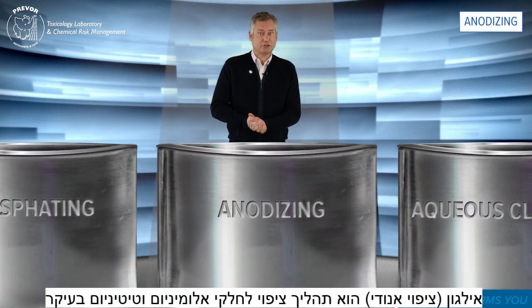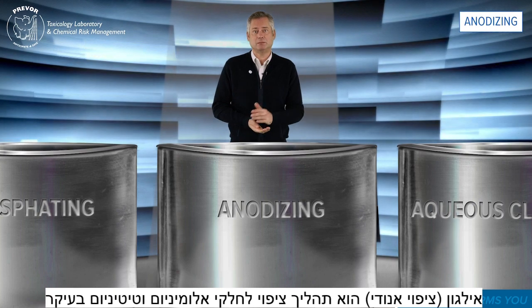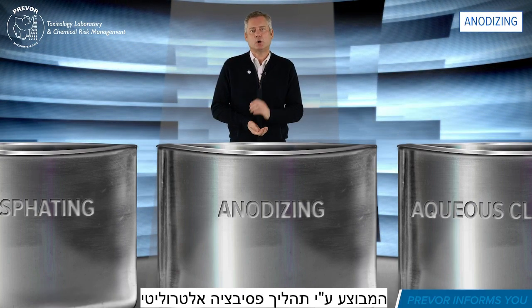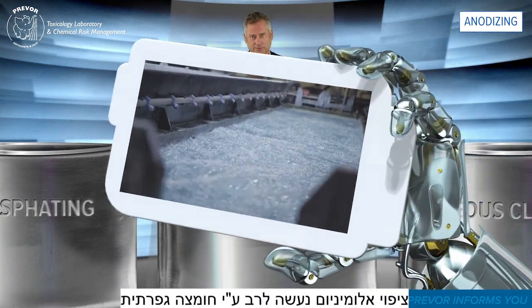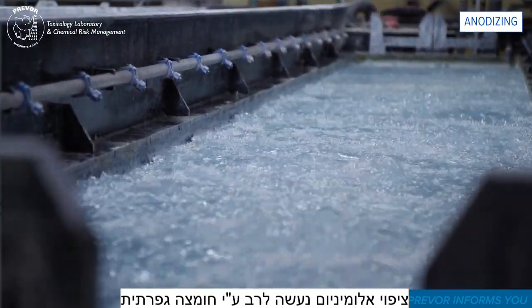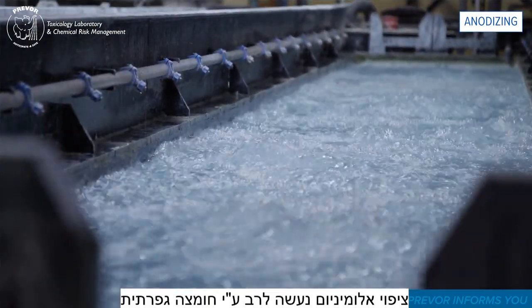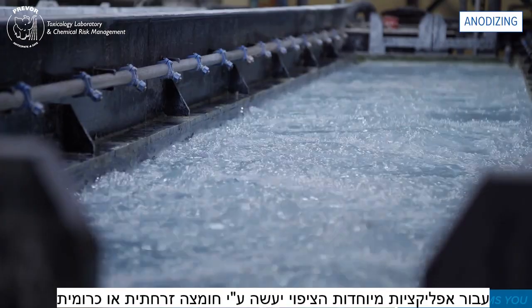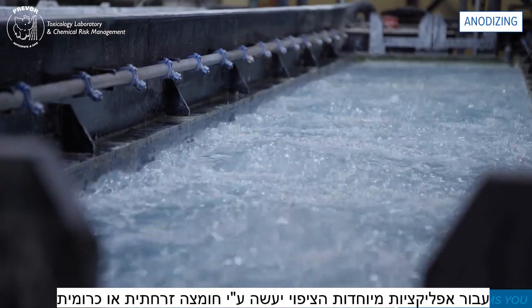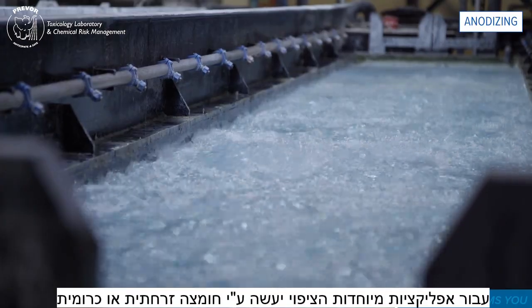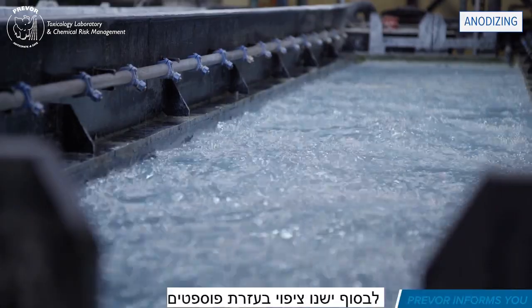Anodizing, in turn, is a surface treatment that protects an aluminium or titanium part by anodic oxidation. Aluminium is usually anodized using sulfuric acid, but for specific applications it can be anodized with other chemicals, phosphoric acid and/or chromic acid.